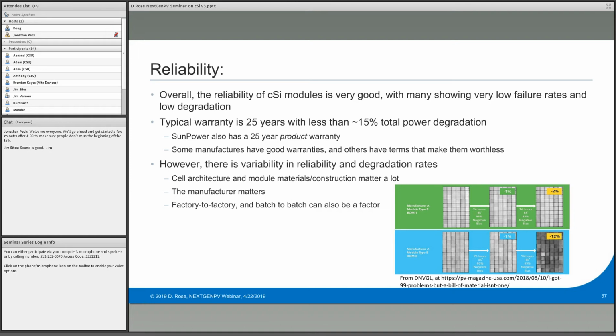Reliability. There could be, and are, entire conferences devoted to recent reliability work. NREL sponsors one of the very good conferences on that. It's a workshop. And overall, crystalline silicon has good reliability, but there is variation. The typical warranty is for 15% total power degradation over the course of 25 years. But there's a range from great warranties to some that have terms that make them pretty much worthless. But that's becoming less common.